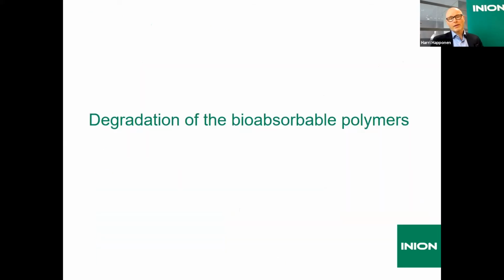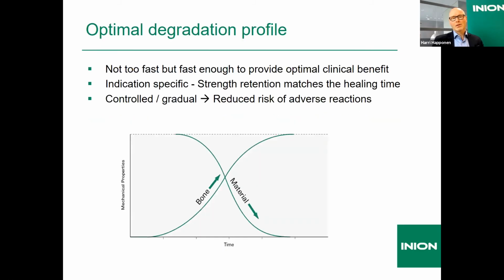Then a little bit about the degradation of bioabsorbable polymers and implants. So of course, as we already discussed a little bit about the too fast and too slow degradation. So the polyglycolic acids were too fast degrading, the first generation polymers, and L-lactic acids were too slowly degrading. So they were not optimal. So that's why it's important to select the polymer and copolymer which is degrading in an appropriate way.